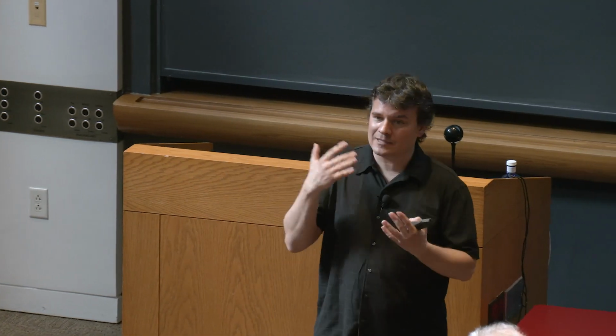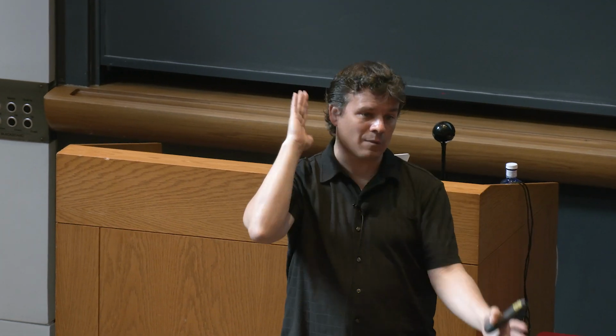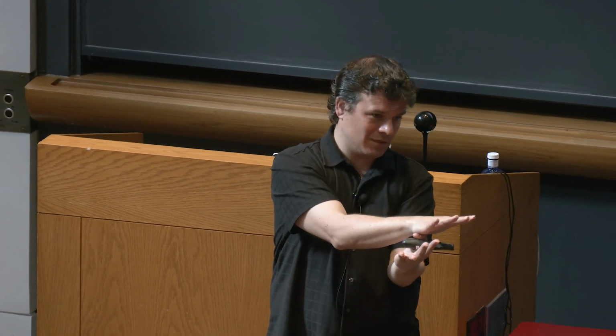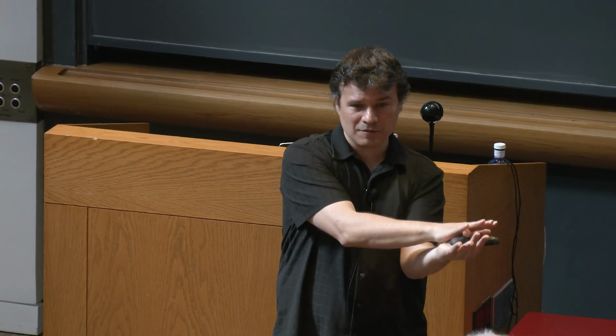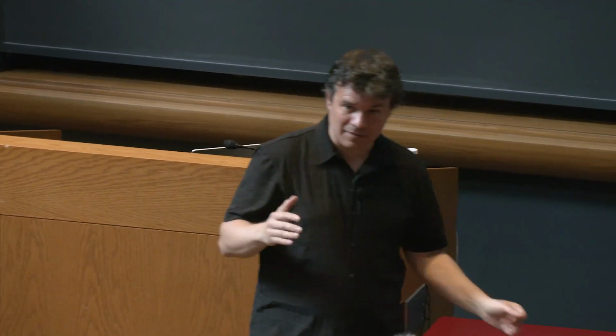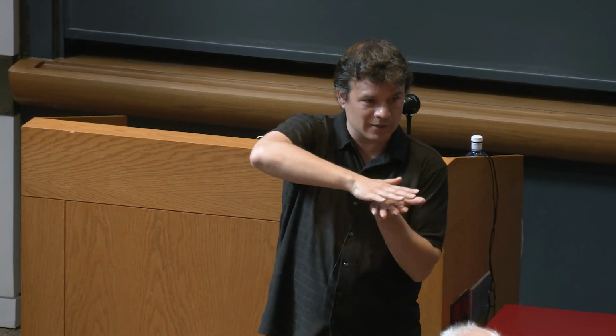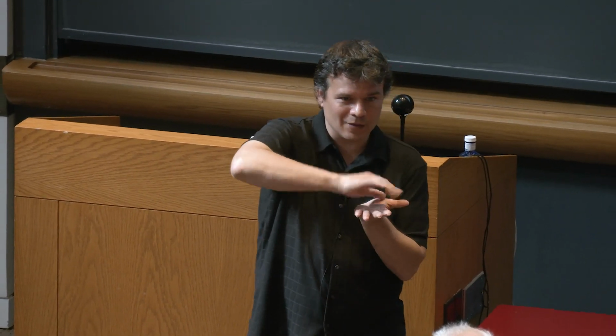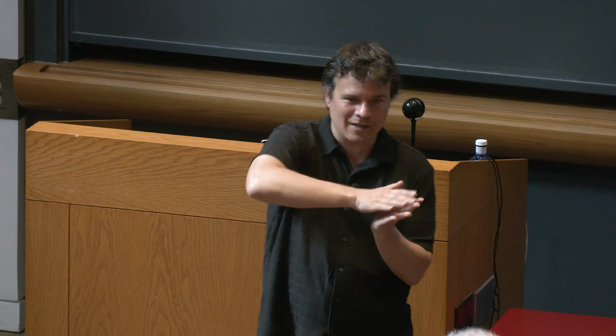And in particular, even a new technique called the quantum twisting microscope has been invented. Now, instead of just slapping these two materials at a given angle, which is fixed, we choose any angle that we want, but once you make the device and put contacts, it's fixed. Now people have invented a method where you can put one on top of the other and vary the angle in situ, and you can study the properties of this thing as you vary the angle. That thing is called the quantum twisting microscope.